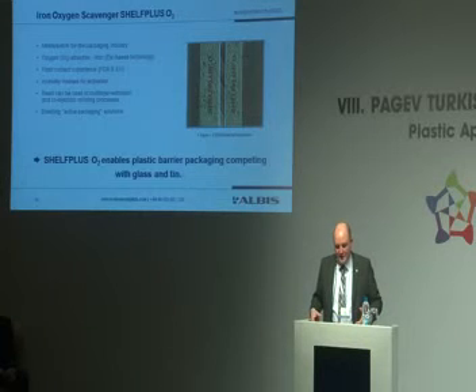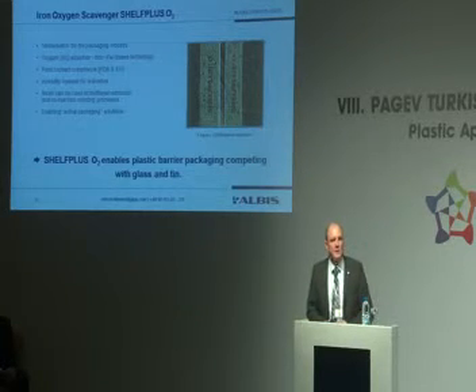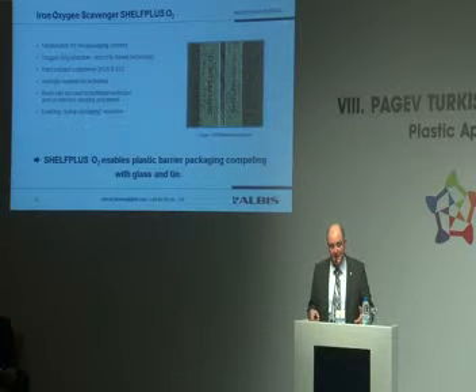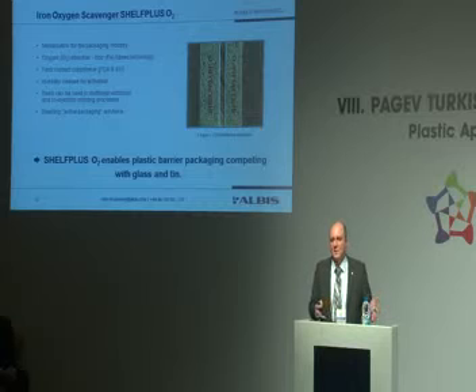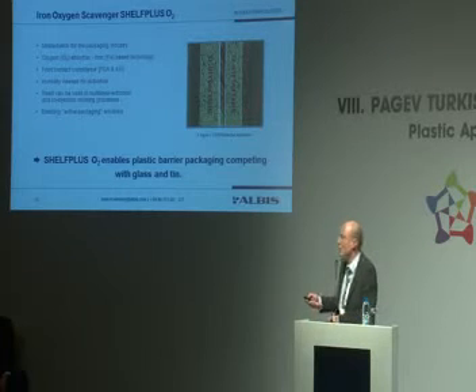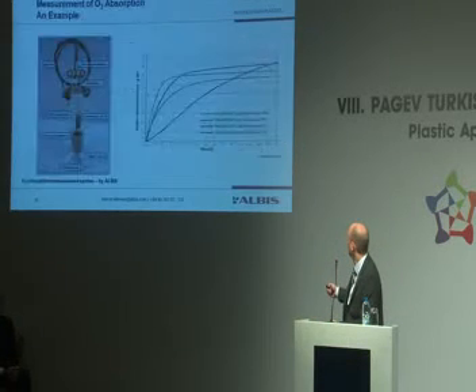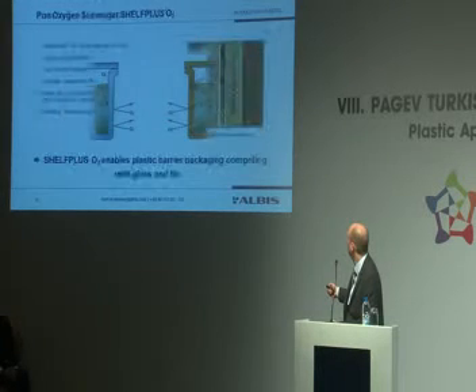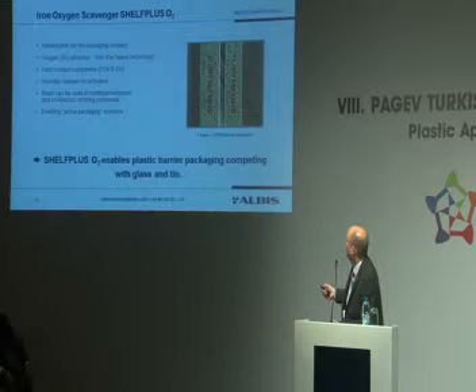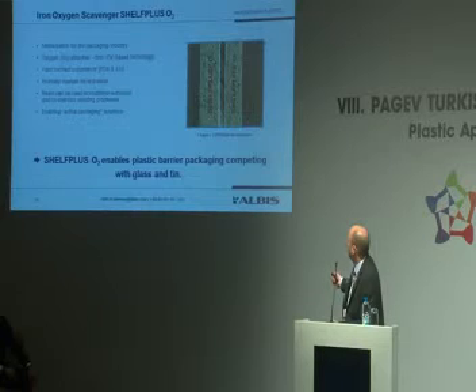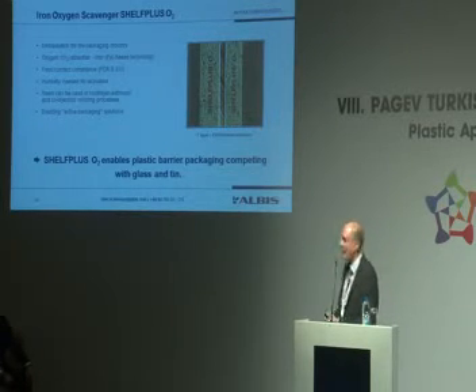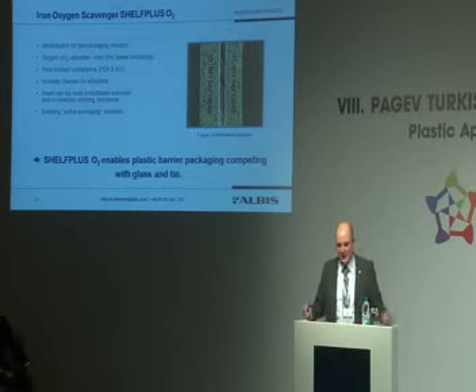Now, oxygen scavenging with Shelfplus. Shelfplus is a product sold by Albis, as you can imagine, and this is basically an iron-containing master batch. It's iron in a master batch form that works as an oxygen scavenger. You can see here a typical structure that would apply the oxygen scavenger. So you have the food, you have a sealing layer, then you have a polymer layer with a Shelfplus, tie layer, EVOH barrier, tie layer, again the Shelfplus and the outside layer. So it's typical to find this kind of products in multi-layer structures.